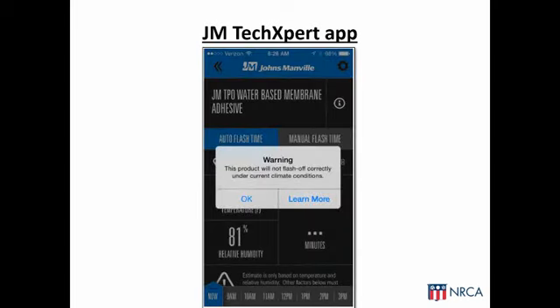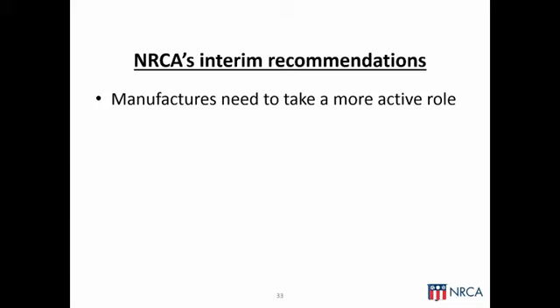Interestingly enough, I checked just this morning and hit the app for here in Chicago, where I'm located, and our temperatures were in the high 20s, relative humidity of 81%, and the app is just coming right out and saying water-based adhesives will not flash off under these particular temperature conditions. And again, I want to get the industry to the point where we're not leaving this decision in the hands of the foreman. The designer should be taking this into consideration and not pushing decisions back on the foreman.